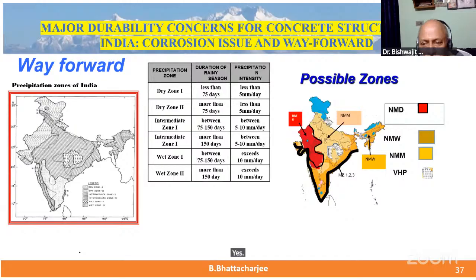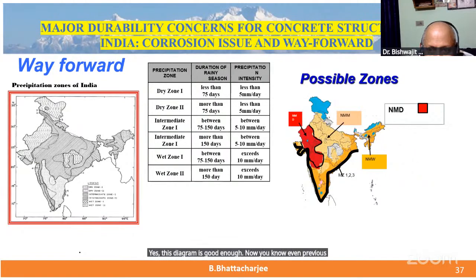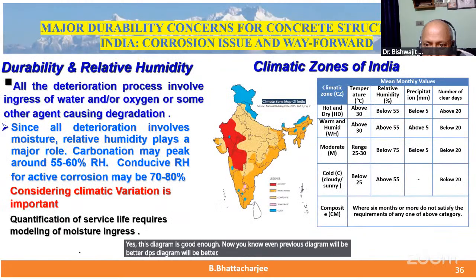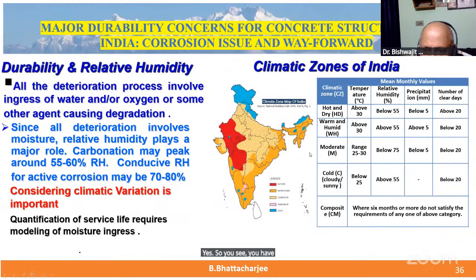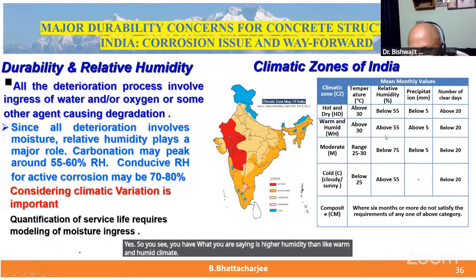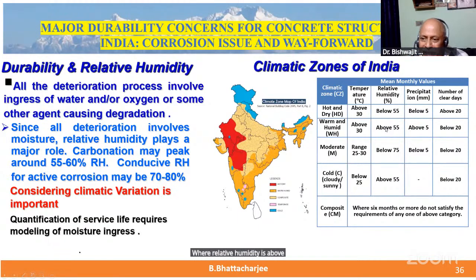Yes, this diagram is good enough. Even the previous diagram will be better. So you see, what you are saying is a higher humidity region like warm and humid climate, where relative humidity is above 55%, right? And the precipitation, I'm not able to see because my photograph is coming here. Precipitation monthly above 5, the number of clear days below 20 days monthly, and for more than 6 months you'll have this kind of weather.